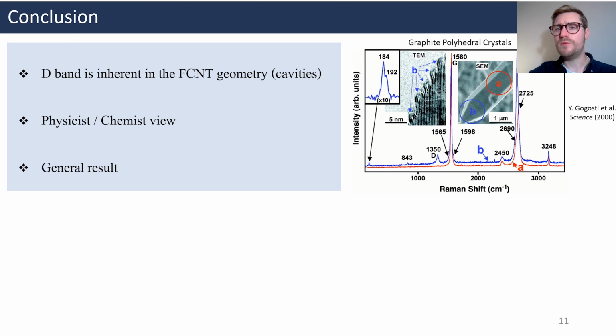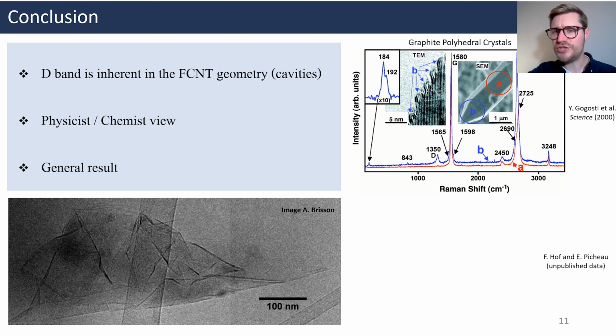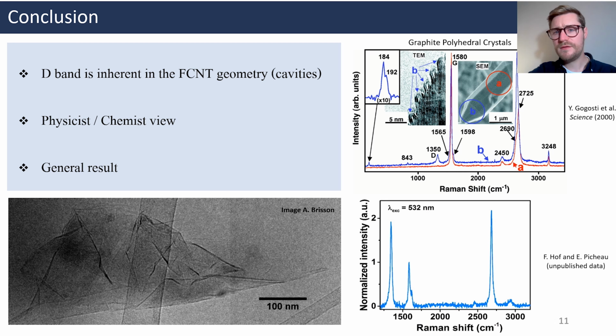It would notably be wonderful to be able to dissociate the contribution of structural distortion and chemist-like defects. Here, for instance, a graphene sheet coming from a surfactant-free graphene dispersion in water. You can see the fold, and on the spectrum, the D-band.